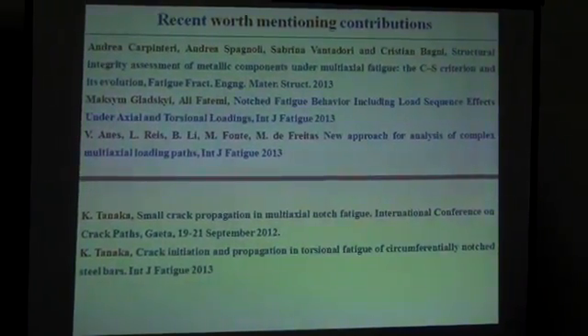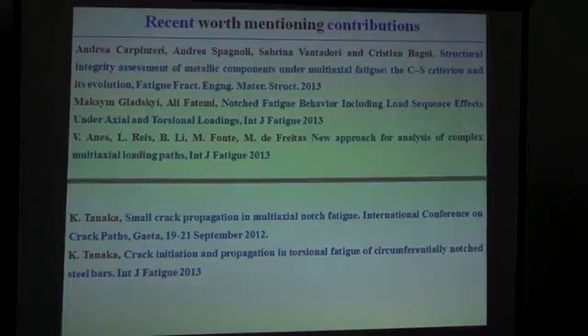Adding this, there are also two very important contributions, in my opinion, that are due to Professor Tanaka, who has shown that there are some cases where the crack propagation is very important, and we have an increase of the fatigue life studying notched specimens in comparison with the plain specimen. It is a very strange phenomenon called notch hardening, which is very well explained in these two papers.